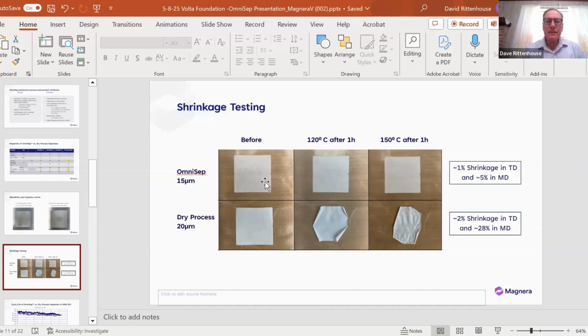This shows, in this top row, our OmniSep 15 micron at 120 degrees C for 1 hour. You see the great difference between a 20 micron stretched film at 150 C, because the fibers are basically randomly oriented and not under stress, very little shrinkage compared to a stretched film separator shrinking 28% in the MD. This is what exposes the edges of the electrodes and causes direct shorts.